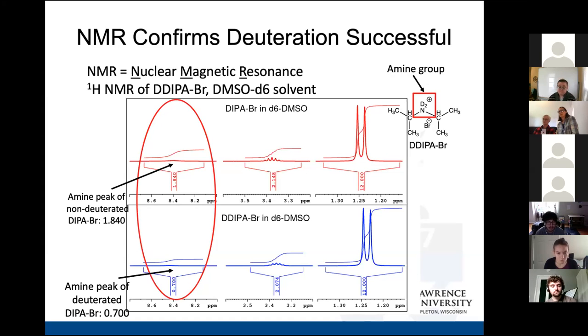This leads to the conclusion that the amine protons are deuterated, while the rest of the compound was left largely unchanged. This also shows that the compound prefers to have the amines deuterated, since the deuterium-hydrogen exchange was at a minimum. If the amines did not prefer to be deuterated, then the deuterium-hydrogen exchange would have been more of a problem, and we probably would have not seen deuterations to the extent that we saw.